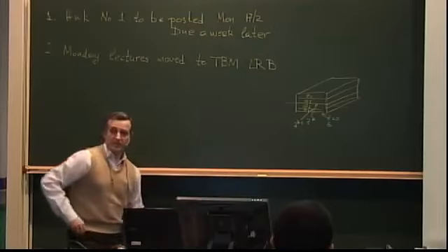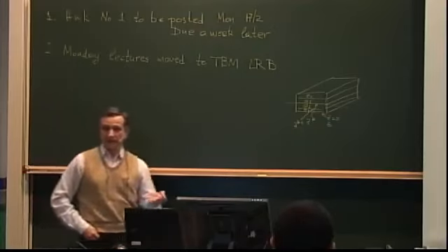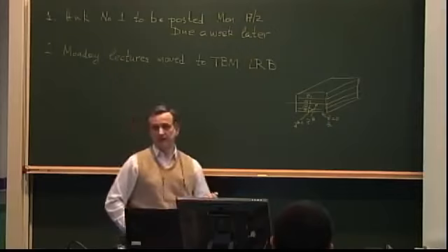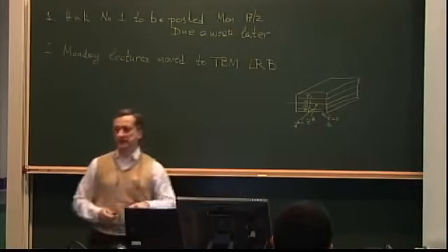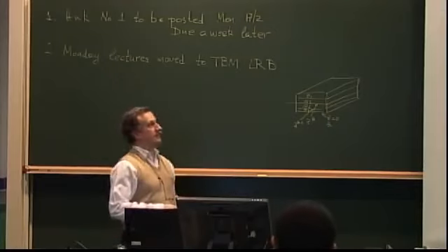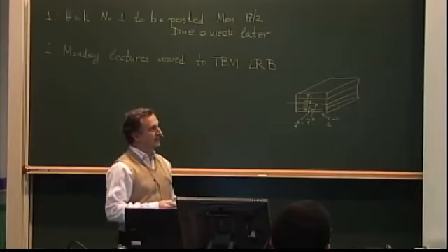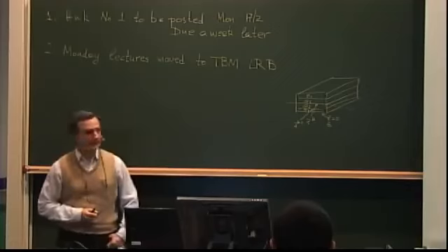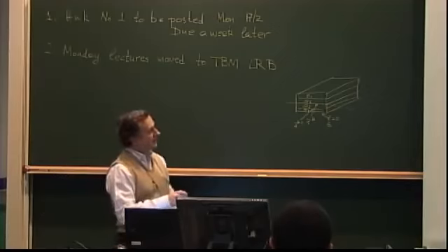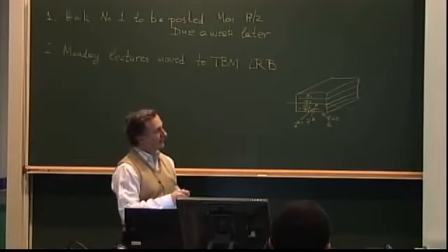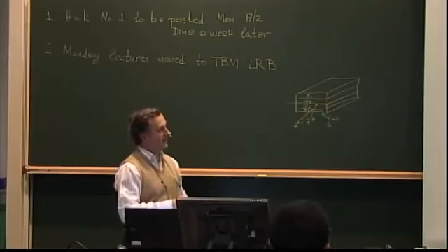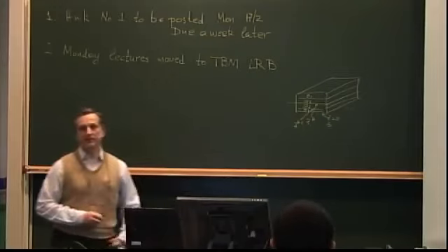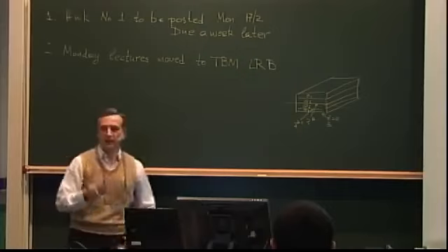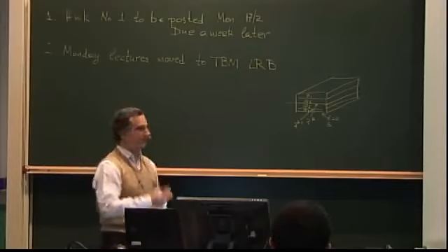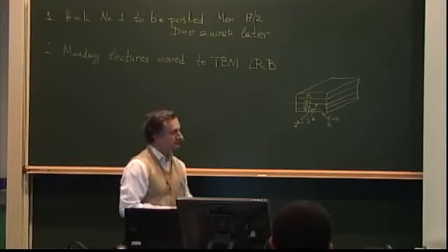Now, if the laminate is symmetric, we said the B matrix, the capital B, or the coupling matrix, is 0. And when you invert it, then the inverted matrix will also have a beta matrix equal to 0. So it ends up being in this form. And then instead of using the alpha matrix, we call it the little a matrix and the little d matrix. The reason is that in the general case, they are not the same. But if the laminate is symmetric, then they would be the same.